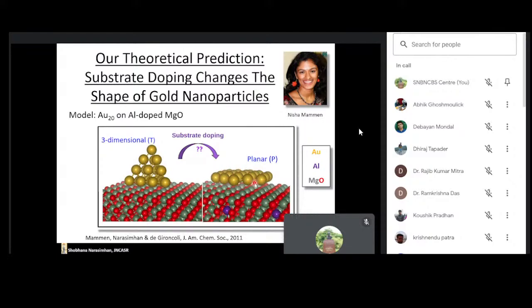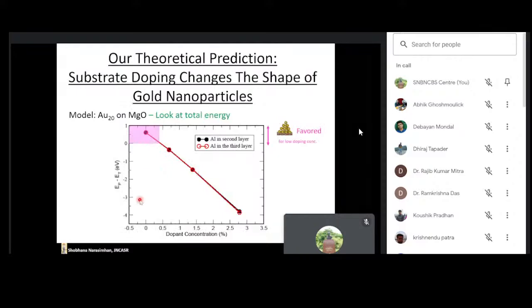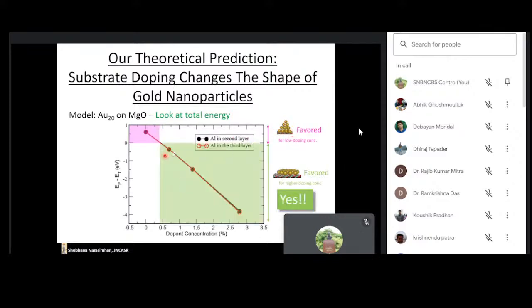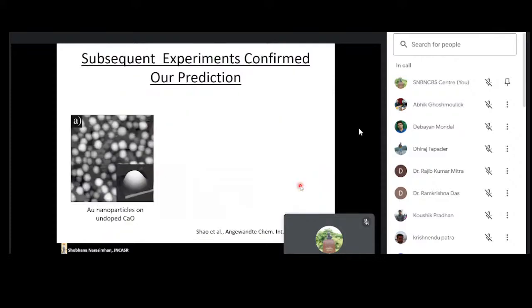So does this work? We did DFT calculations. So this shows the energy difference between the planar and tetrahedral shapes of the nanoparticle versus the concentration of the aluminum dopant. So at small dopant concentrations, the three-dimensional shape is still favored, but above about 0.4% doping, you find that the planar shape is indeed favored. And soon after we made this prediction, the experiment was done. The experiment was done on a slightly different system. Instead of a magnesium oxide support, they used a calcium oxide support.